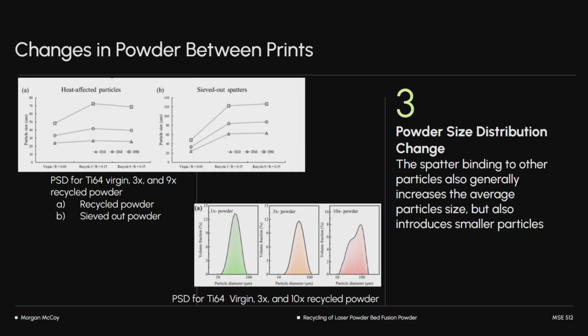Finally, there is a change in the powder size distribution. The spatter binding to other particles increases the size and generally increases the average particle size, but it also introduces smaller particles. On the top left, you'll see PSDs for Ti 64, virgin, 3X and 9X recycled powder.